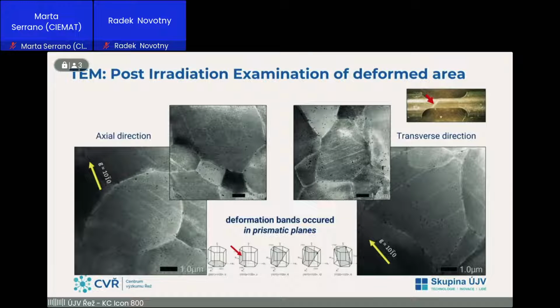And these are the images of the place which is marked on the specimen. So this is the specimen taken from the deformed place directly, and we can observe the deformation bands within the grains in the prismatic planes of hexagonal lattice of zirconium alloys.